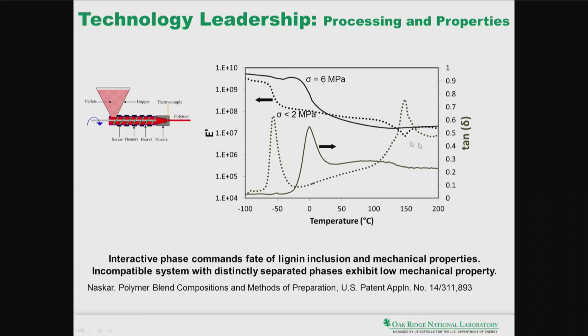So then this particular product did not show a great mechanical property. It was less than 2 megapascal. Then we did the interfacial adhesion of those two phases by tailoring the chemistry. And once that was done, then we saw a significant jump in the mechanical properties, 6 megapascal tensile strength in that material. And you can see now the rubber softening point is close to 0 degrees Celsius, and lignin softening point got closer to the rubber one. So there is a great improvement in compatibility in the blend, and that was the reason for improved performance.